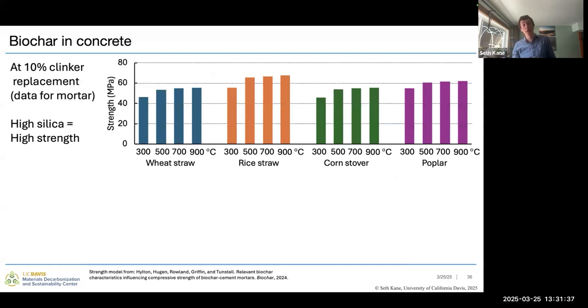And so now thinking about the outcomes, this is leveraging a predictive model for biochar properties that we developed in our group, specifically for thinking about biochar life cycle inventories, as well as that strength model developed by the folks at Colorado School of Mines and NREL. They're looking at 10% clinker replacement, reporting strength here for a mortar that is about 44 megapascal strength with no biochar added. You'll remember here that our rice straw was our high silica content biomass, and we can see that that results in the largest increase in strength.